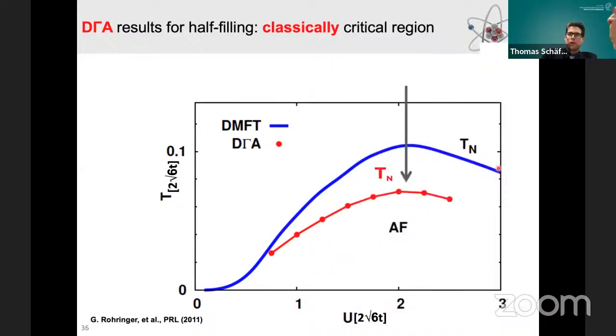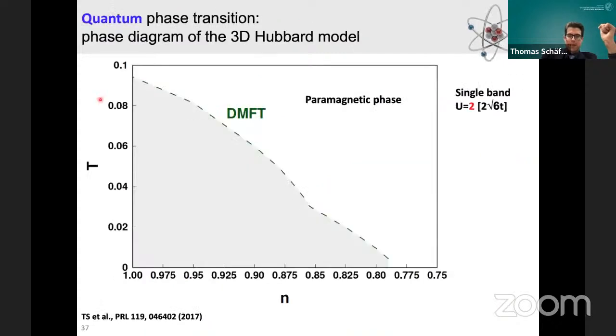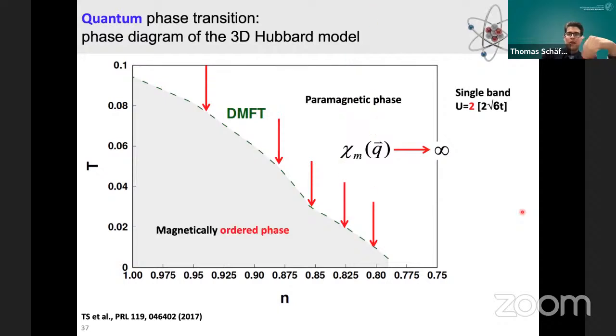Now we go one step further, and we dope the system. So we introduce holes into the system. What happens then? So in DMFT, we see that the Néel temperature as a function of this hole doping drops, and we also eventually get down to zero temperature. Again, we calculated this phase transition line by calculating the magnetic susceptibility and its divergence. If we now include on top again spatial correlations, this Néel temperature drops a bit.